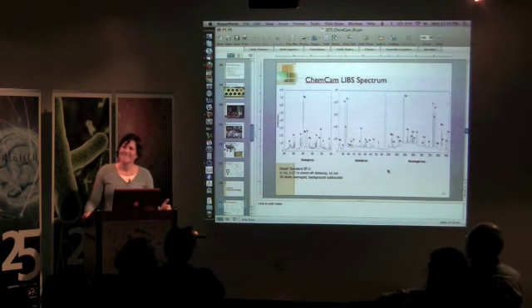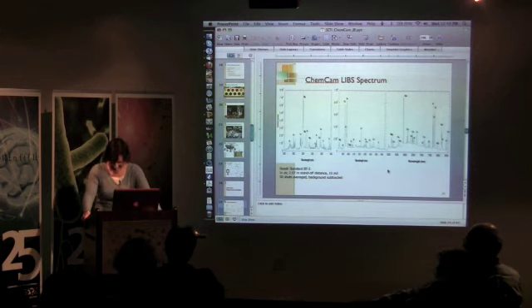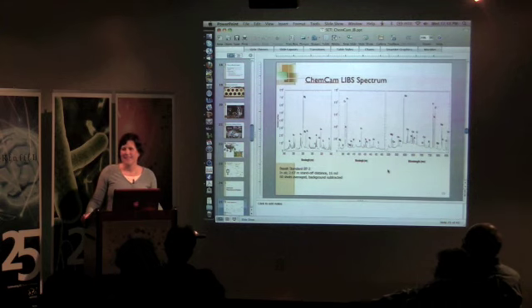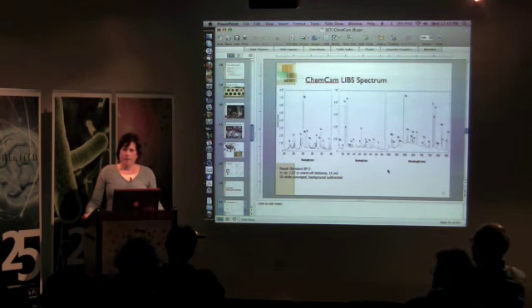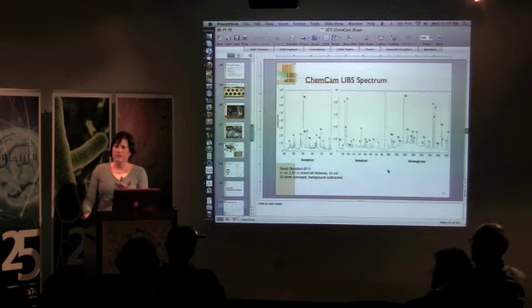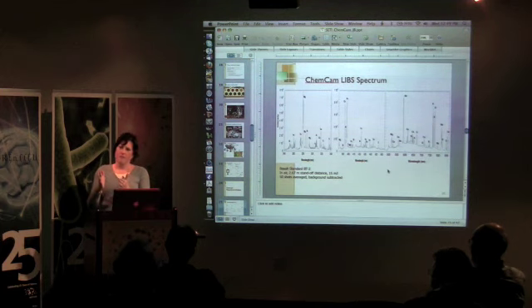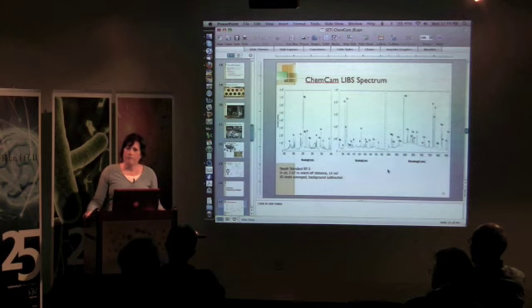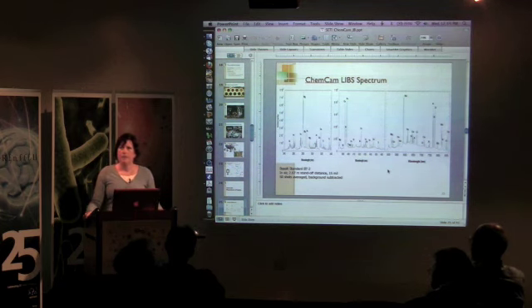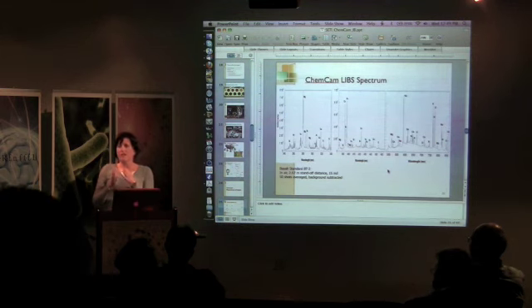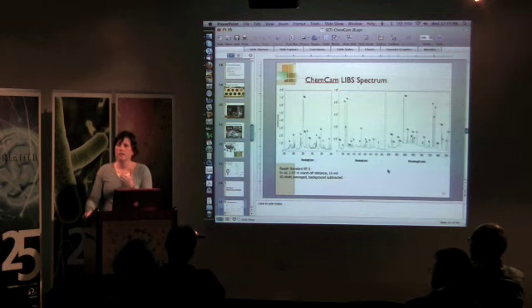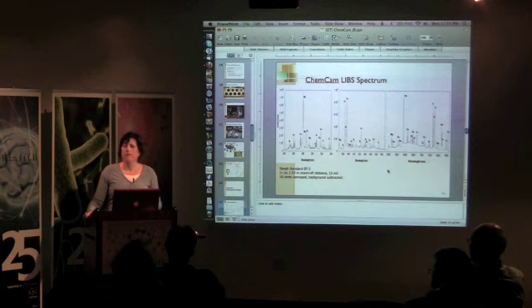I have another question about the alignment of the LIBS with the microscopic imager. It seems like it would help if you can take an image during the LIBS pulse to actually locate the spot on the surface. Would the sequence be like, you take an image before, then during, and then after, and use those to align it? That's a good point, and yes, they're supposed to be used in tandem. You take the image and then you can essentially see the pit from the LIBS measurement afterwards, and you can take another image. Can you image during it to see the spot, or only afterwards? I believe because of the data collection transfer, it's pre or post. It's not synchronous. But the hit is pretty obvious. In theory, they're supposed to be co-aligned. The RMI is essentially the same tool. Are they actually mounted through the same optics? Yeah, they are. Okay, that's great.